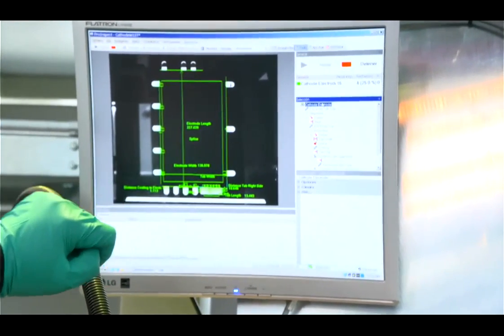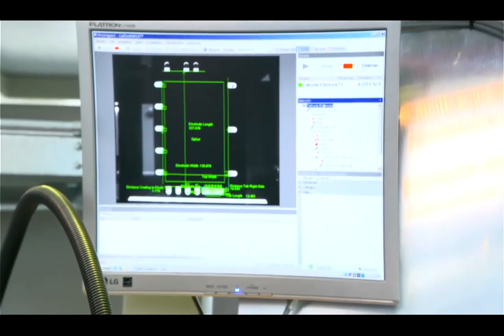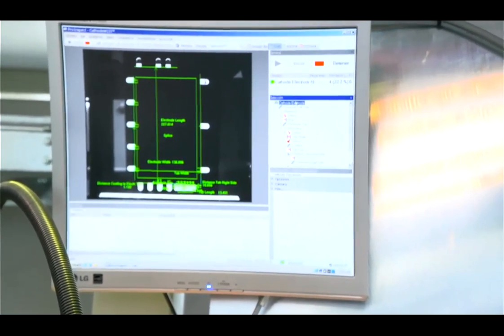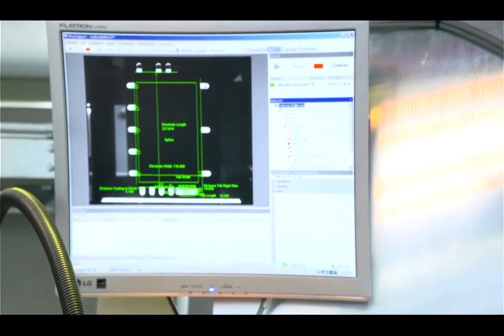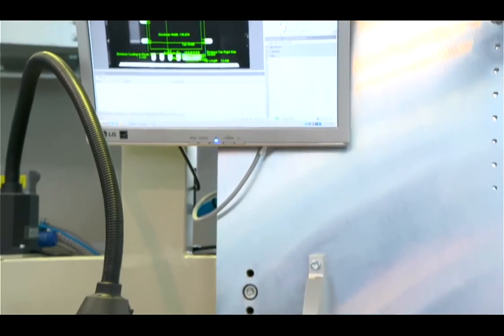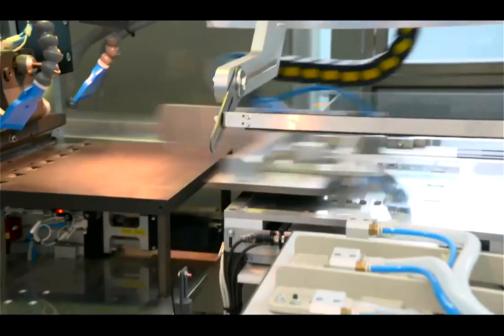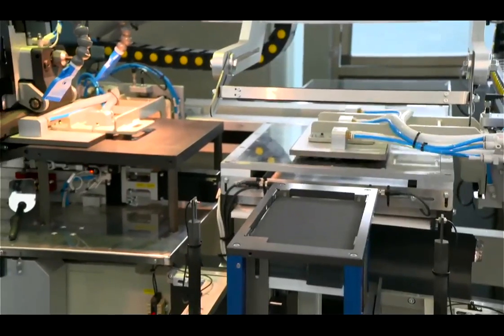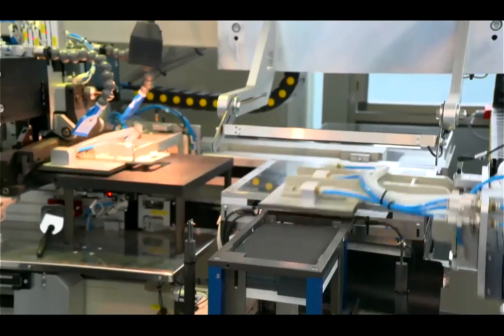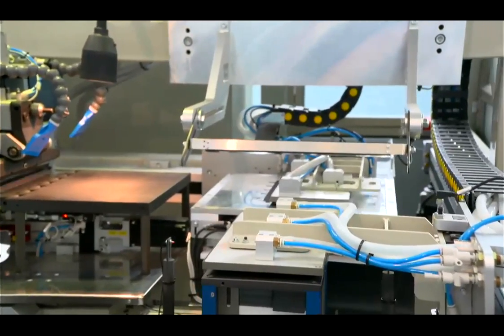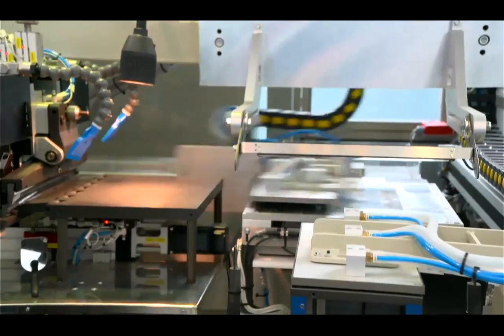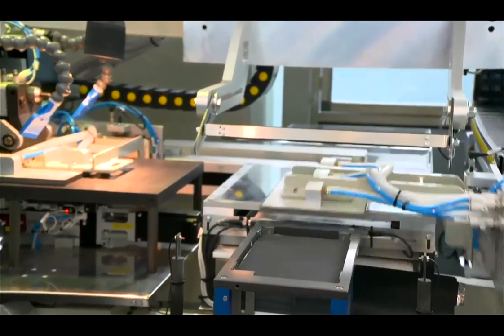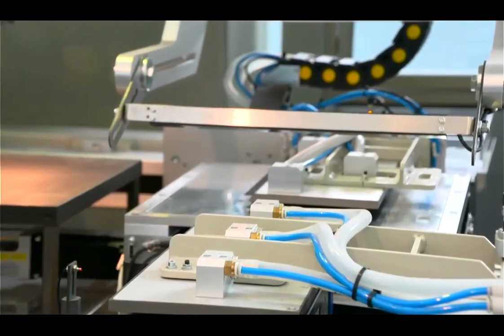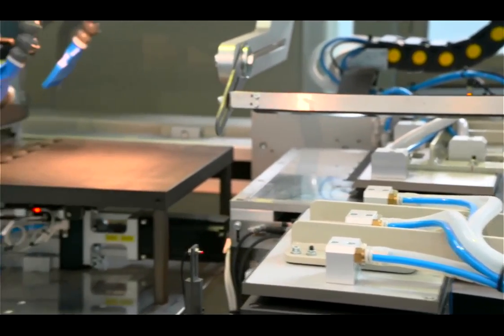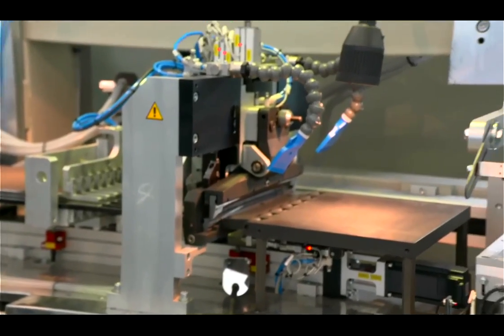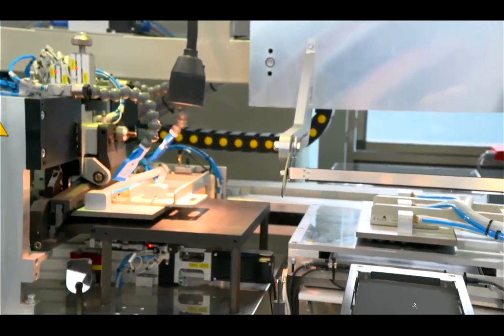And we have some tolerances that are 100 nanometers. If in the cut we see a 100 nanometer deviation, the machine automatically discards this electrode and puts it in the back part. Now it's taking all the electrodes, so you can see that the cut is very clean. Maybe Iker can take one electrode just to see how the edges of these electrodes are. He stopped the machine, and I think now he is going to take an electrode.